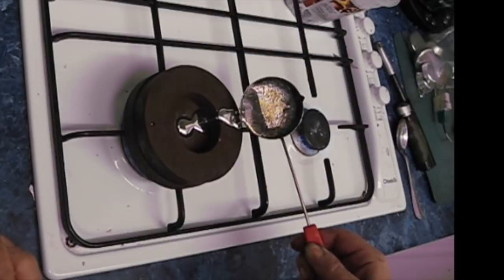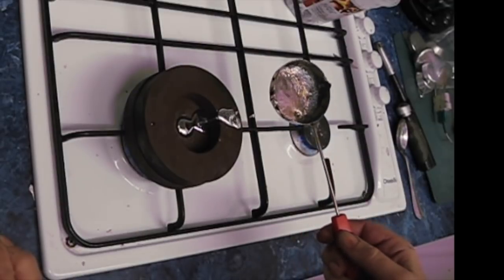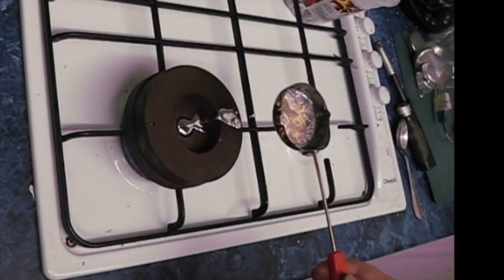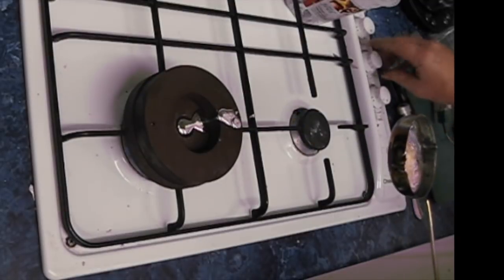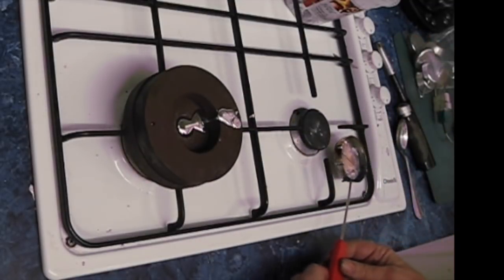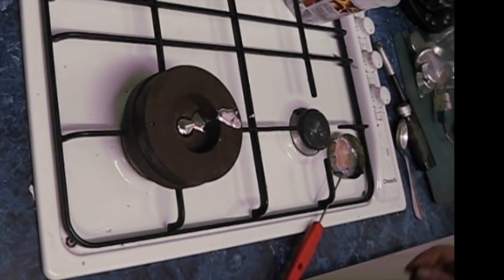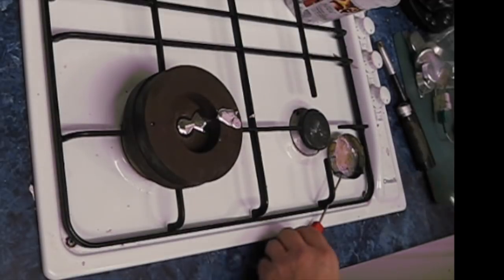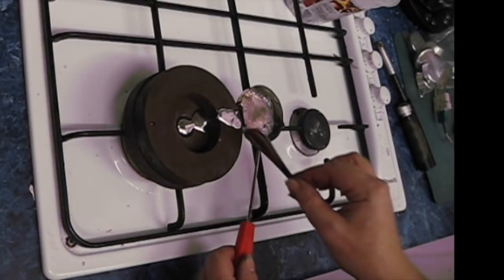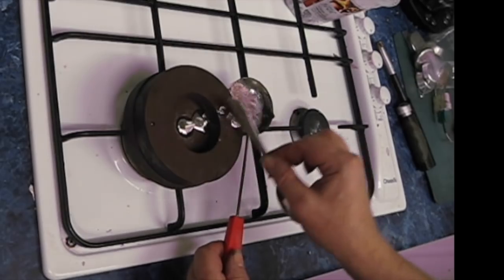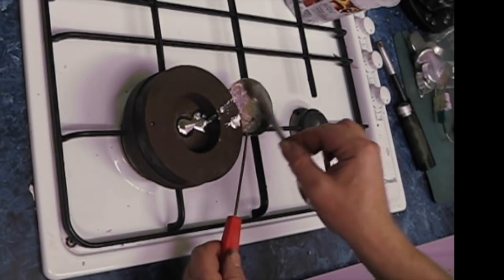You can see because the mould is warm, the pewter stays liquid quite a long time. And just on the left you can see it's risen all the way up the riser. So that does mean the mould is completely full. The fact that the mould is preheated means that the pewter stays liquid for quite a long time, so I can scrape off the excess.